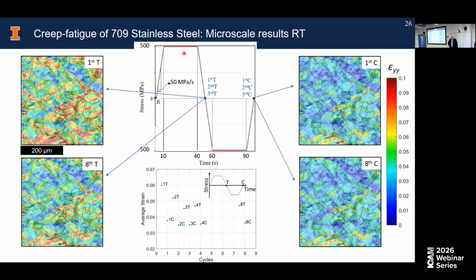Again, what this shows is the evolution of the microscale strain field with dwell time in creep fatigue. This is at the end of the first tensile cycle. This is at the end of the first compressive cycle. There's a lot of things you can study here, like strain reversal, and that's what this project is about, but I won't go through that detail. What I'm interested in here more is the evolution with cycling. So this is at the 8th cycle, tensile and compressive.